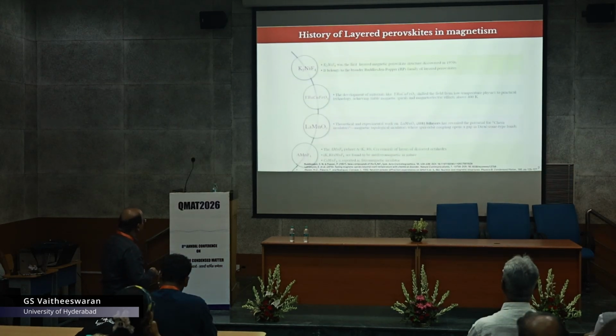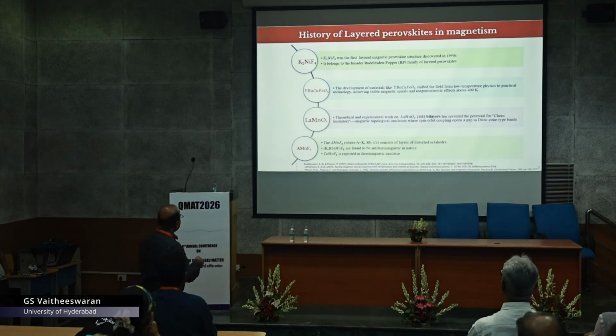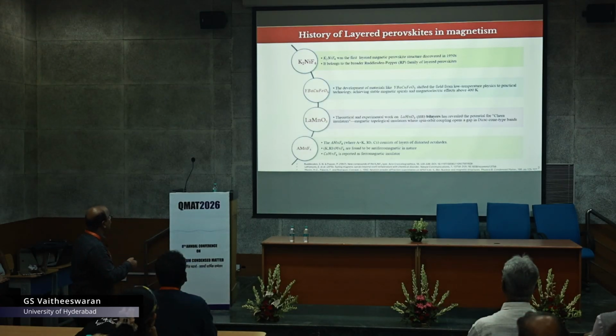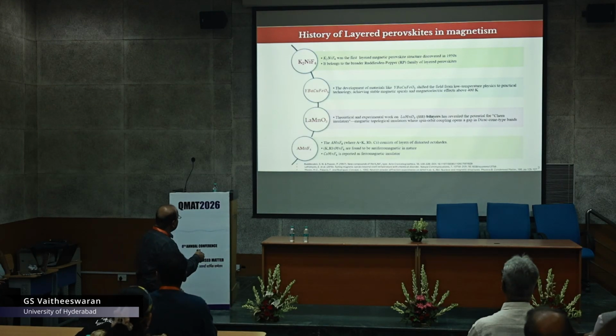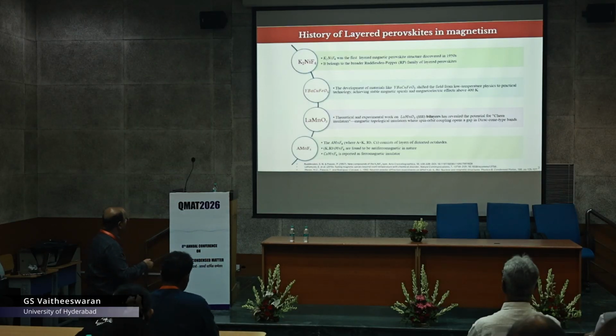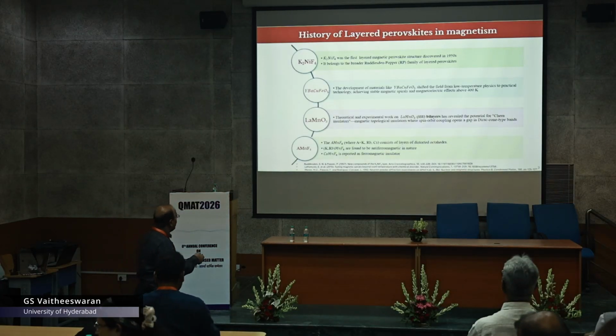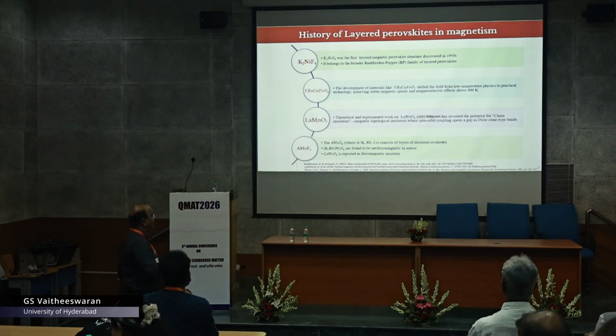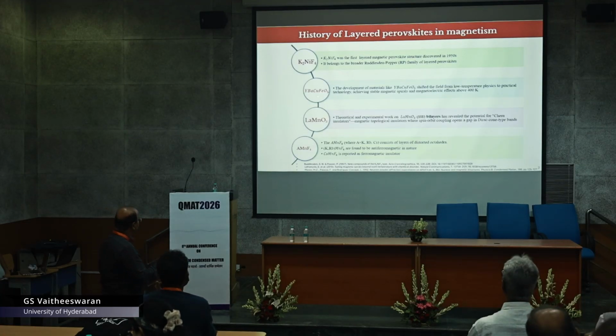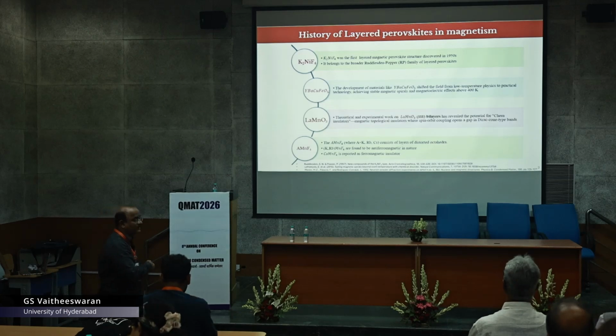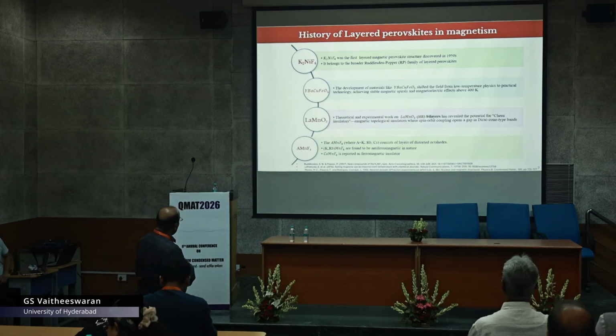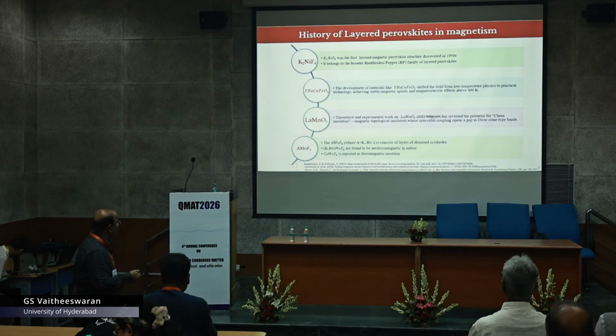This is not very new, and it started in the 1950s, where they reported K2NiF4, which has a structure similar to perovskite but with a tetragonal lattice, and it broadly belongs to the Ruddlesden-Popper family of layered perovskites. Then came the quaternary or even more complex yttrium, barium, copper, iron, oxygen 5, and then came the popular lanthanum manganate, where we have several structural distortions, and the whole doping story relates to ferromagnetism and so on.